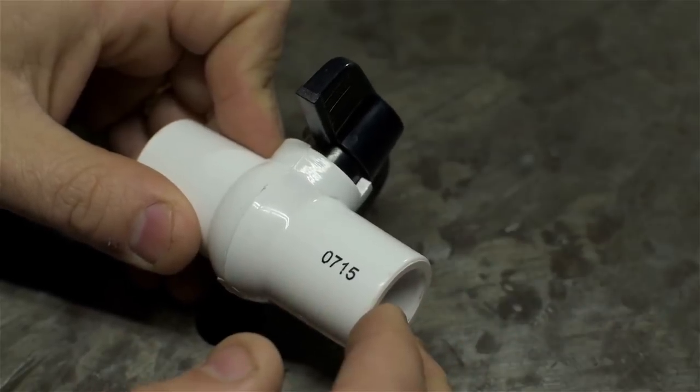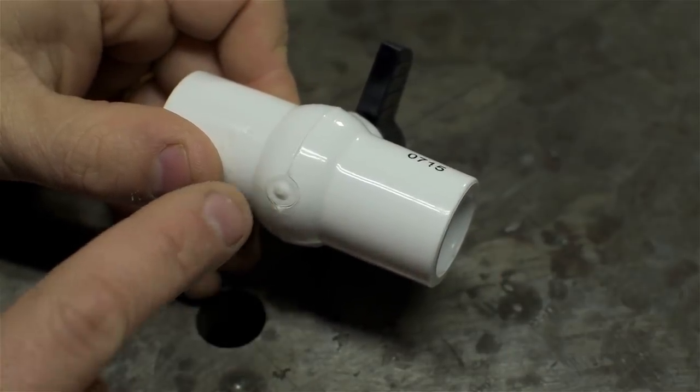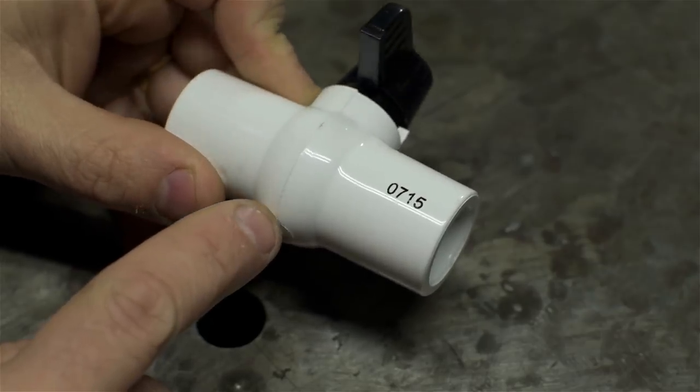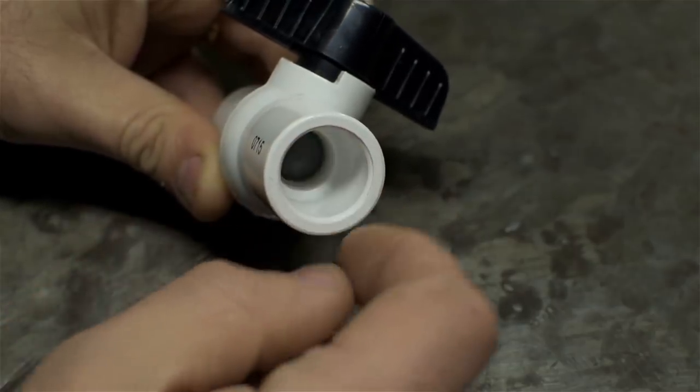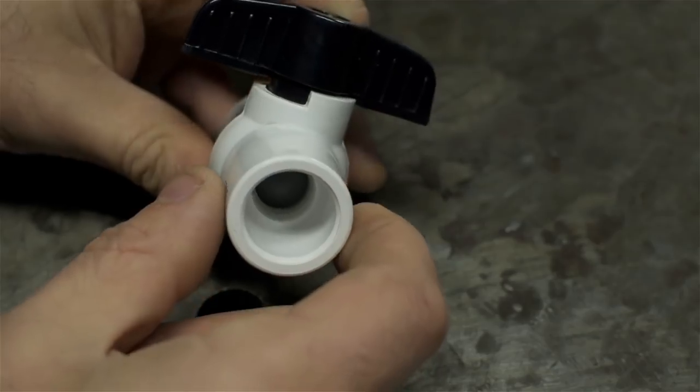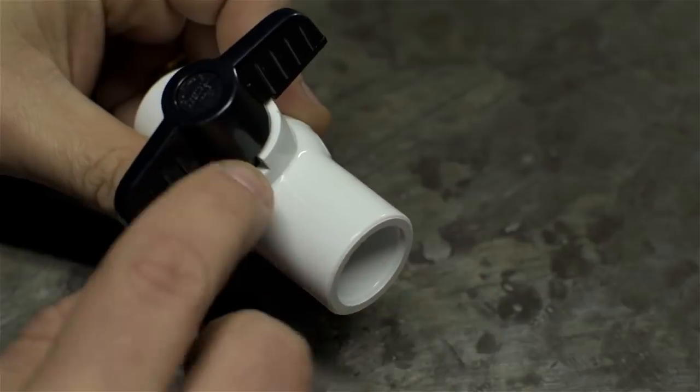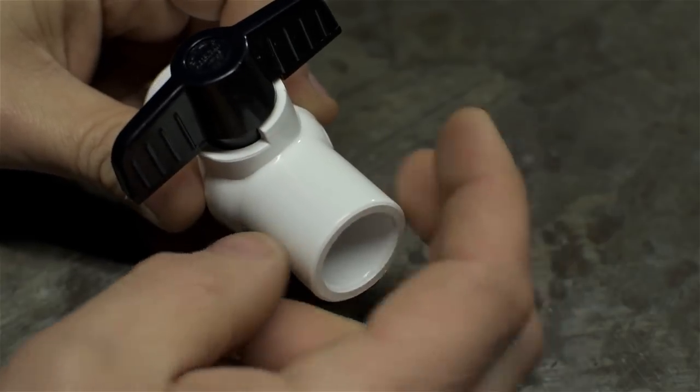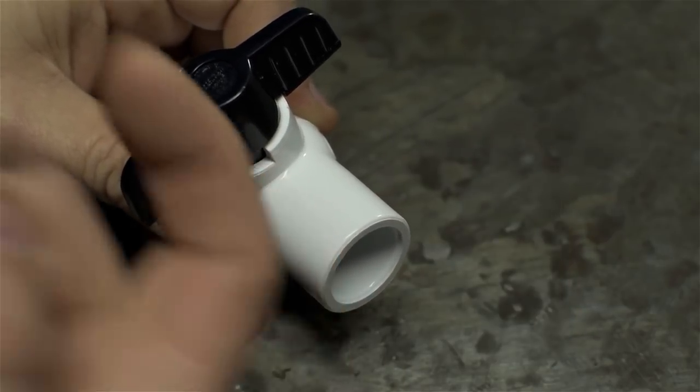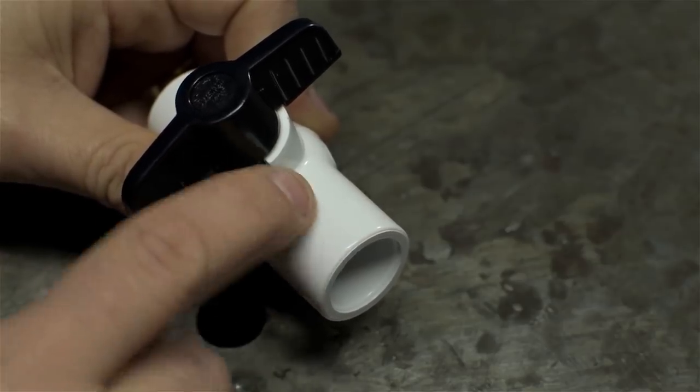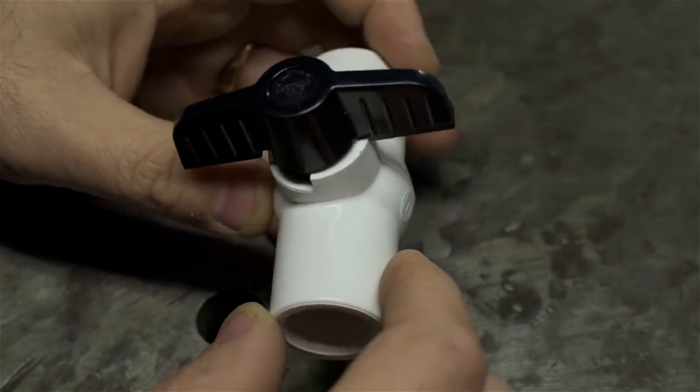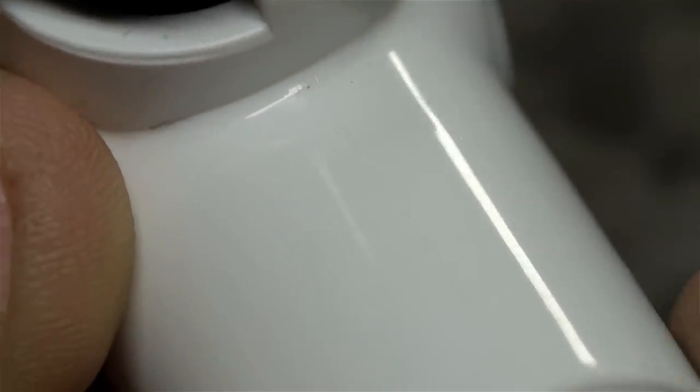So that's where they squirted the plastic into the mold. It started here, under pressure, and started to slowly fill this cavity up. You can imagine the plastic flowing its way around the steel that was creating the opening for the half-inch pipe that will eventually go in here. Those flow fronts met up here at the top. And where they meet, they create a weld line. There's plastic flowing up here. There's air inside of the empty space in the tool that's kind of being burped out. And the two flow fronts of plastic meet somewhere up on the top edges because it's being pushed in from the bottom. Now, I can see that weld line. Let me see if I can get you a better. In person, it's almost impossible to see. I can't feel it under my fingers. But you could just see it as it sort of like plays in the light. What looks like a dark hairline going down the length of the part.